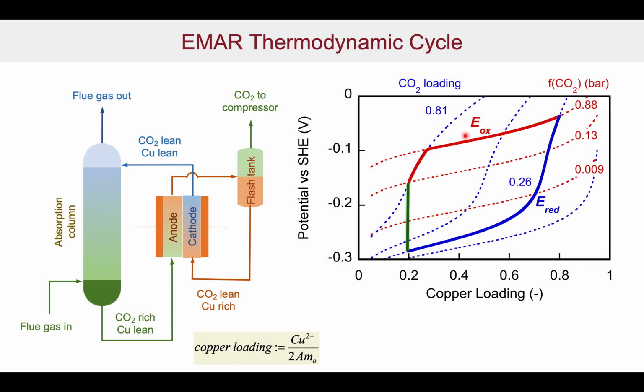The red lines are the constant fugacity. So this could be considered to be the system pressure, for instance, if you're looking at pure CO2 in the system. So what we can look at now is what is the thermodynamic cycle in this particular process? Well, if we look here, at this particular point we've got gas coming in. The copper load is only about 0.2. We've got gas that's in equilibrium with a fugacity of about 0.13, about 13% CO2.